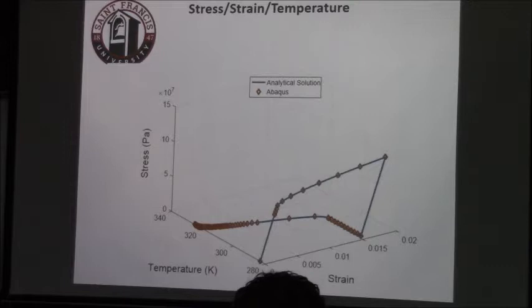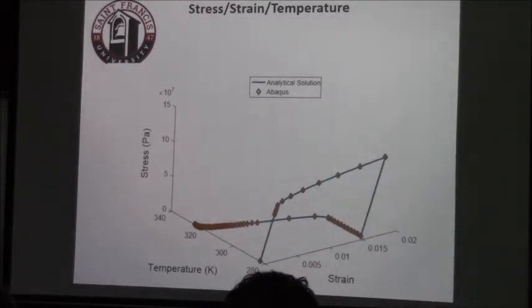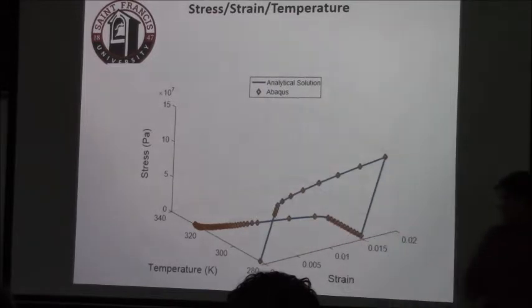And I just showed it, okay? There we go. And so this is an analysis that we did with a typical one. And again, what's showing is kind of the same thing except for the temperature. But here we have stress, and here we have strain. And from your thermodynamics class, I don't know if you remember having a diagram that was a PV diagram. And the area that the cycle made in the PV diagram was the work. Well, stress basically is like a pressure, and dV is like a strain. You're changing the dimension. So this area basically is a reflection of the amount of work you can do, or the amount of work that you've done on your shape memory alloy, that might be available over this modest temperature range available to use.